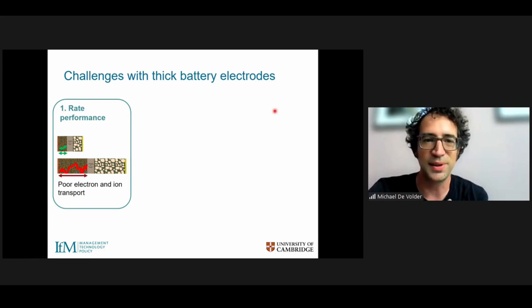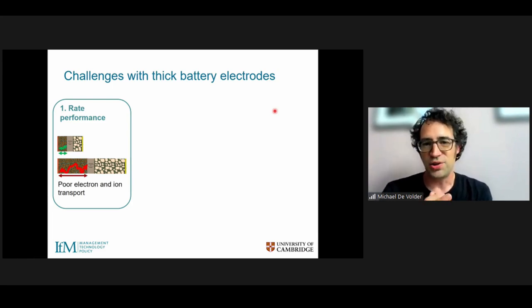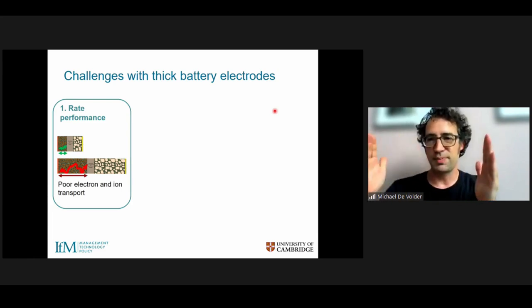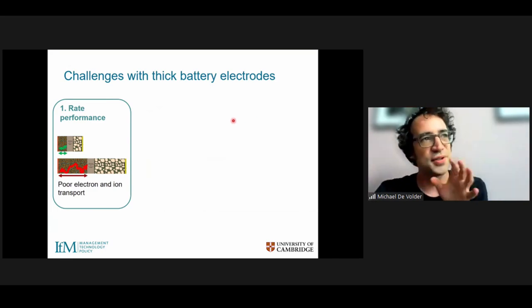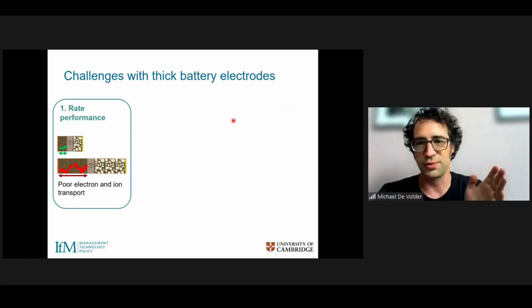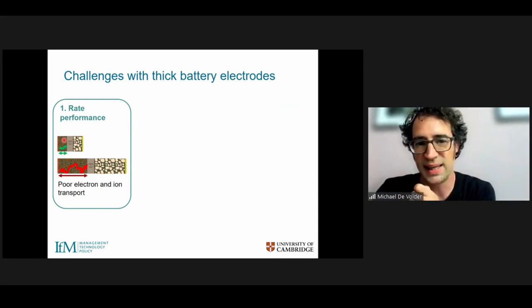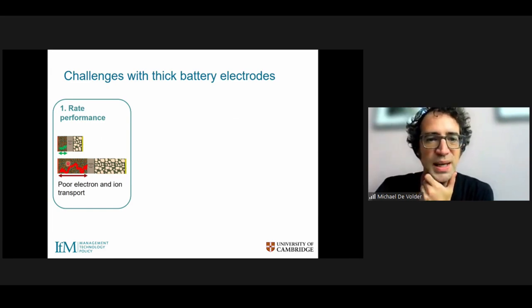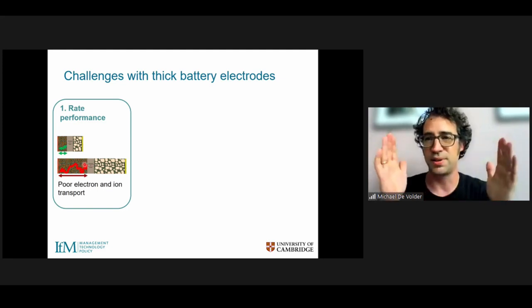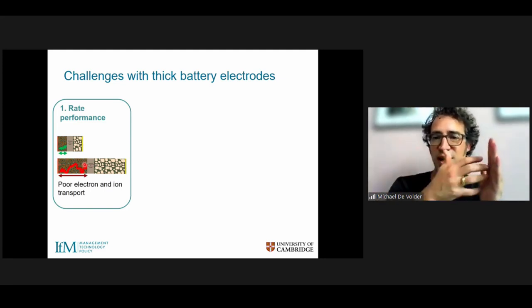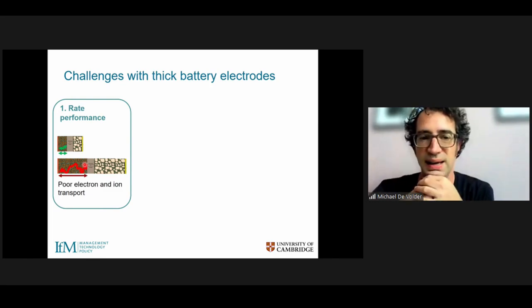electrodes at the moment? Well, you can imagine that if the electrode becomes thicker and thicker, ions and electrons will find it much harder to travel through the electrode. So if you have a thin electrode as depicted on the top here, the electrons go back and forth quite easily. If the electrode coating becomes too thick, the ions will take too much time to diffuse through the electrode, and that will lead to, for instance, very long charging times of your battery.